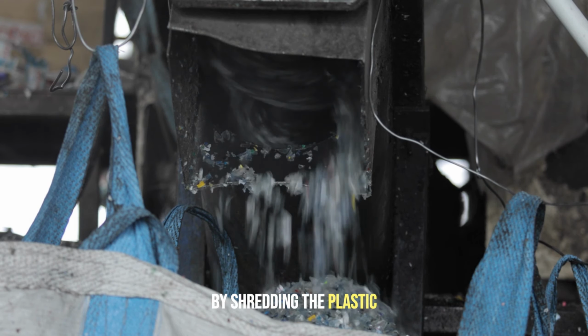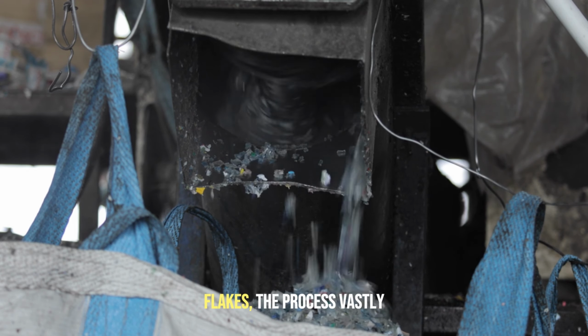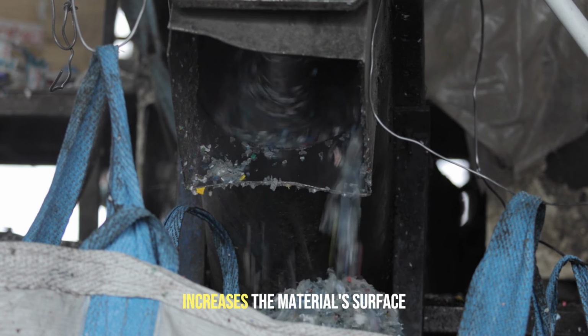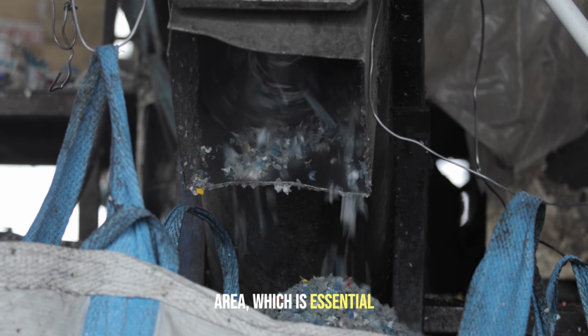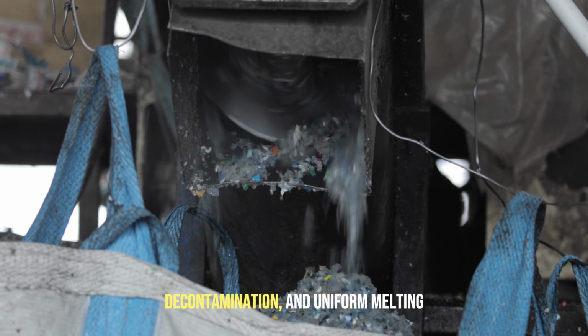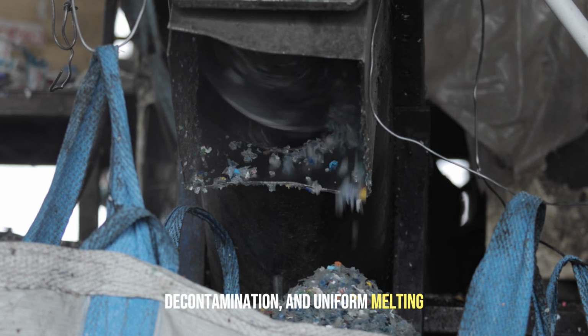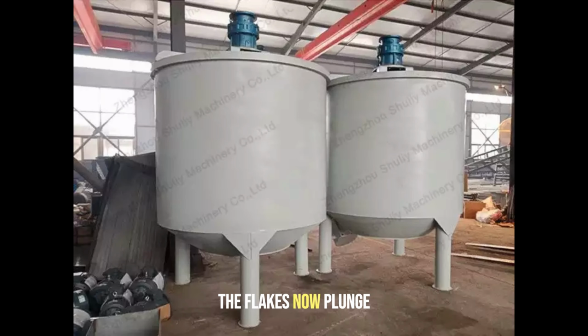By shredding the plastic into these small, consistent flakes, the process vastly increases the material's surface area, which is essential for more effective cleaning, decontamination, and uniform melting in the stages ahead. The flakes now plunge into enormous hot water tanks filled with detergents, a 1 to 2% sodium hydroxide solution heated to 80 to 95 degrees Celsius, where they are agitated for 10 to 20 minutes, effectively dissolving adhesives and allowing labels to detach and float away.